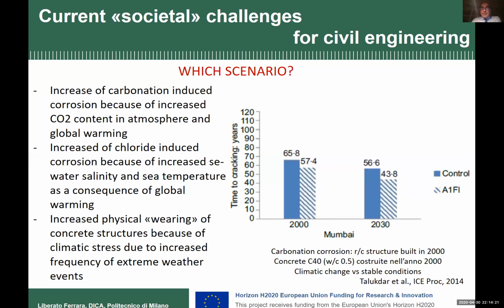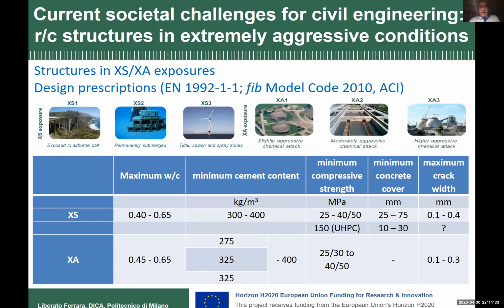Well, this is just one of the examples. And we know that for structures which experience these aggressive conditions, we have in the codes prescriptions on how to design structures which can guarantee a minimum expected service life. So for chloride-induced corrosion, I use here the notation and symbols and prescriptions of the Eurocode, which is the standard and code I am used to. So chloride-induced corrosion, we call condition XS. We have some prescriptions about the maximum water cement ratio, minimum cement content, and minimum compressive strength.